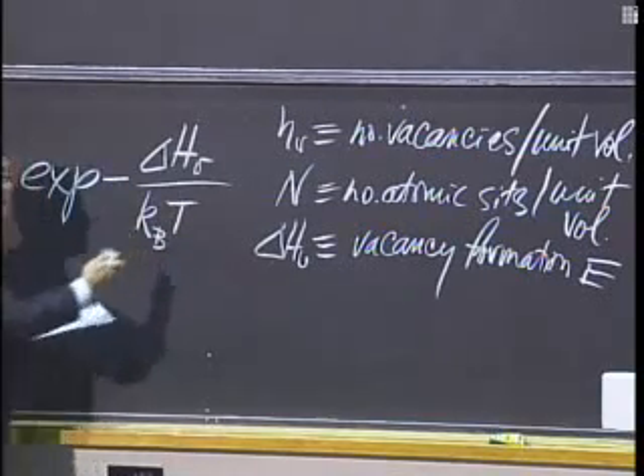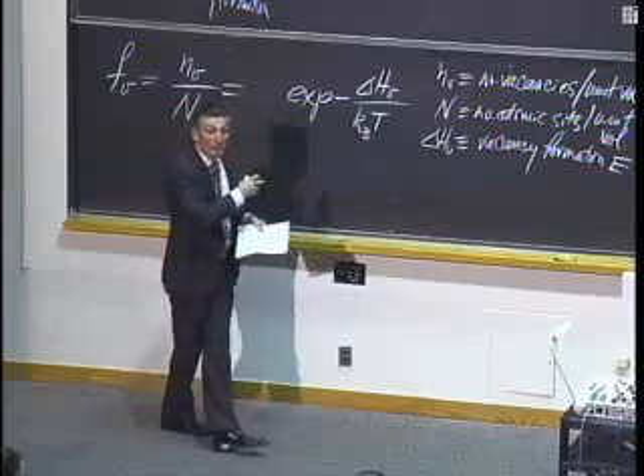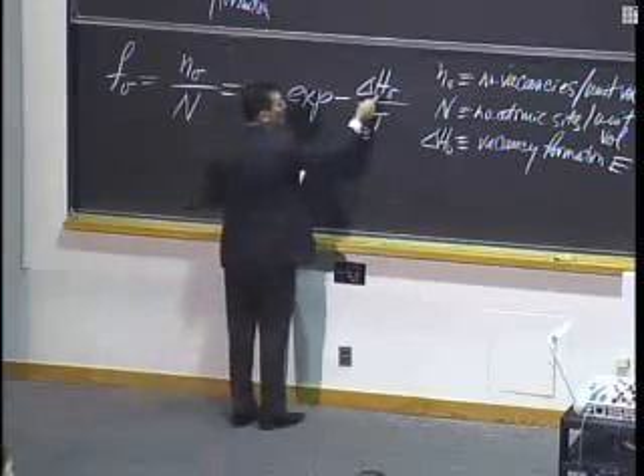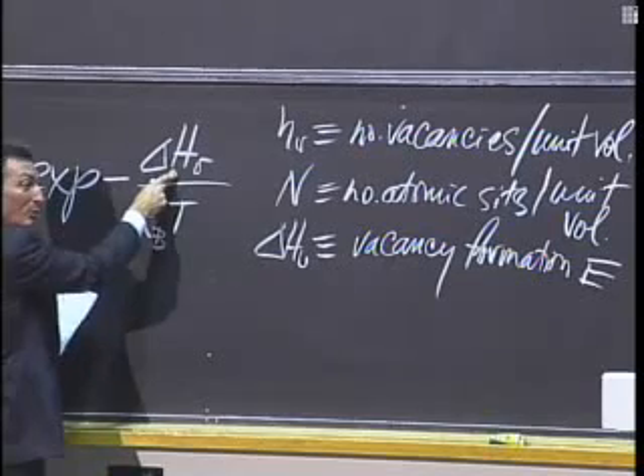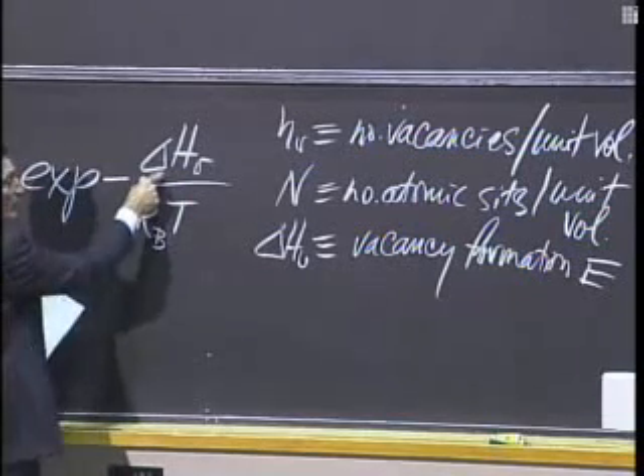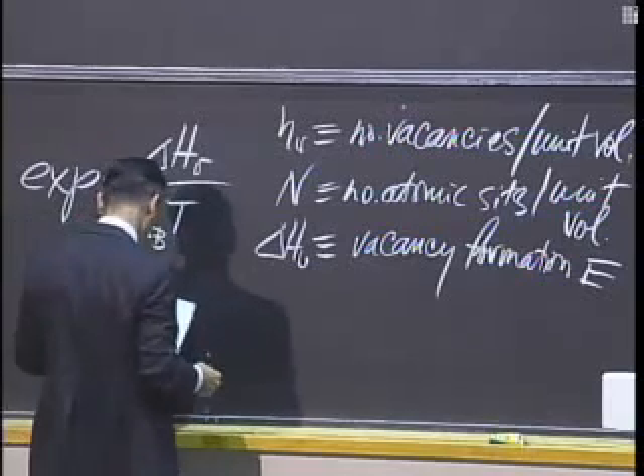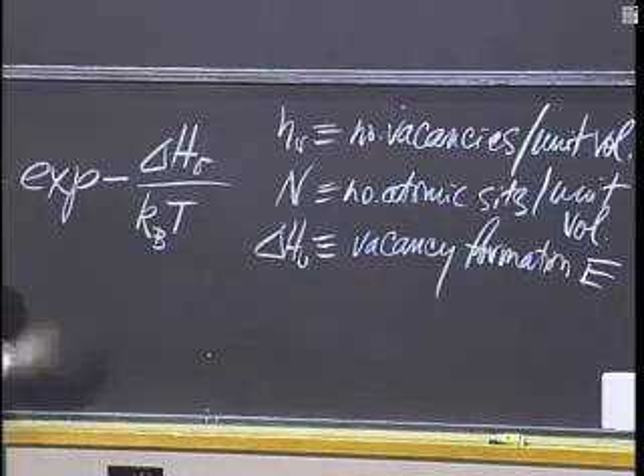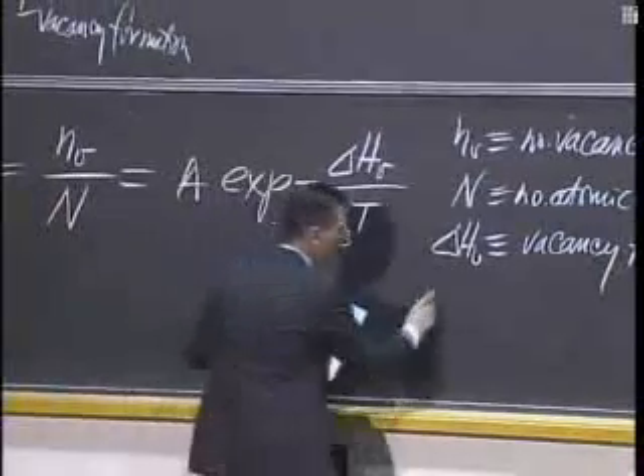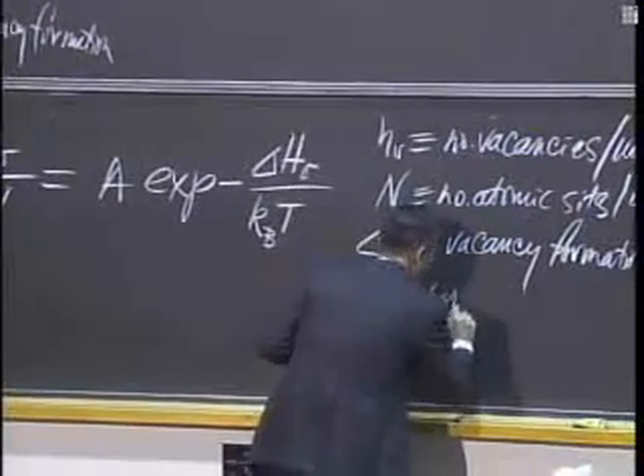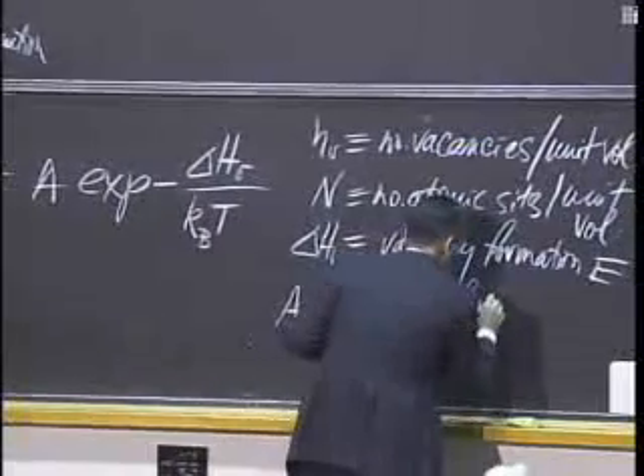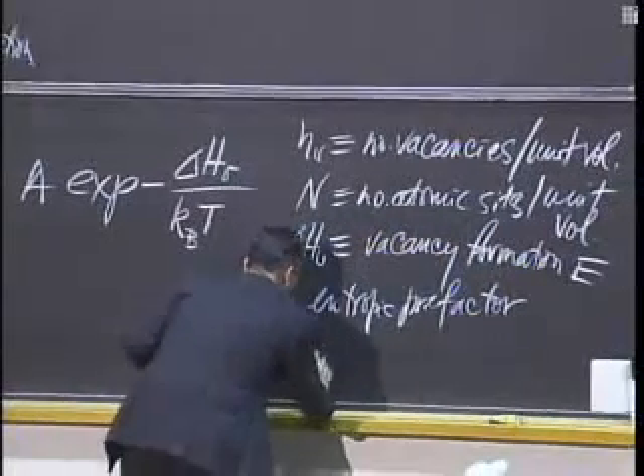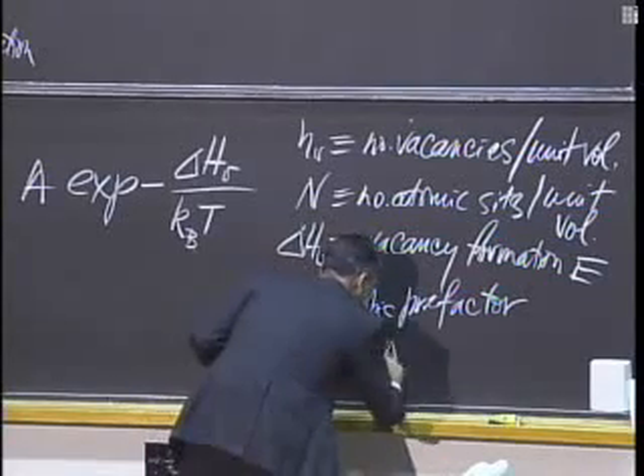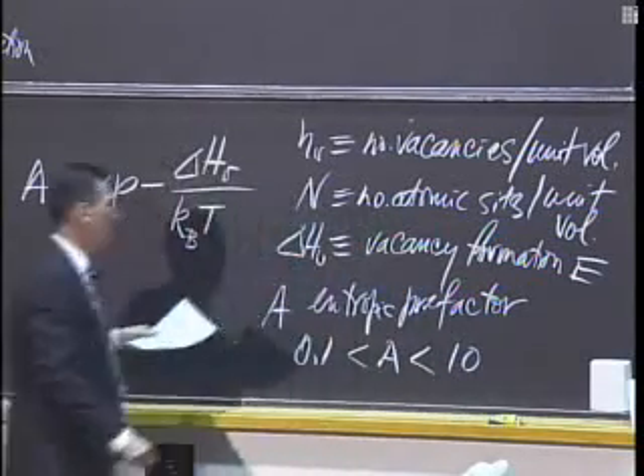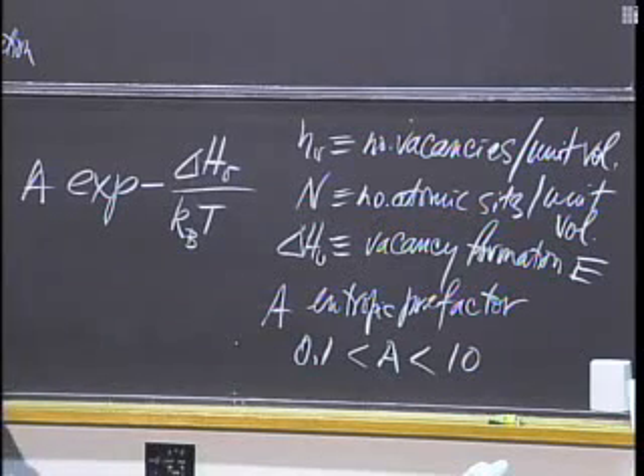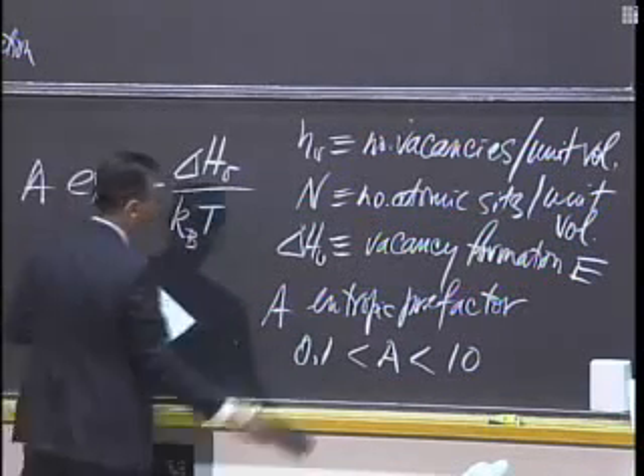So what are we doing? We're taking this onto the temperature distribution, and we're saying, where is this required energy in relation to the average energy of the system, and in particular the high-end tail. And then it has a prefactor A, and A is just an entropic prefactor. And it's not equal to 1. A will take values between a tenth up to about 10. It's typically on the order of 4 or 5, something like this, but in some cases it can even be